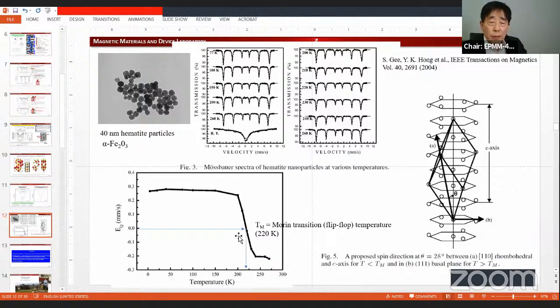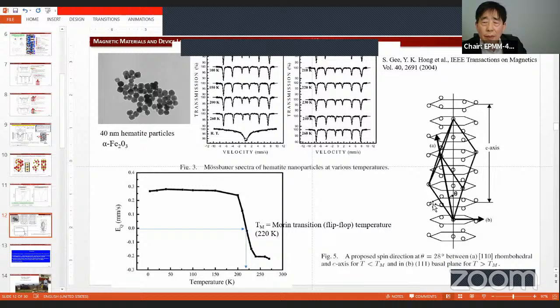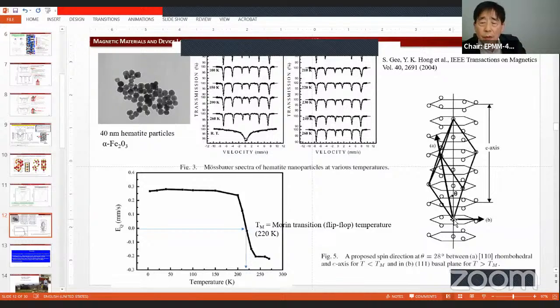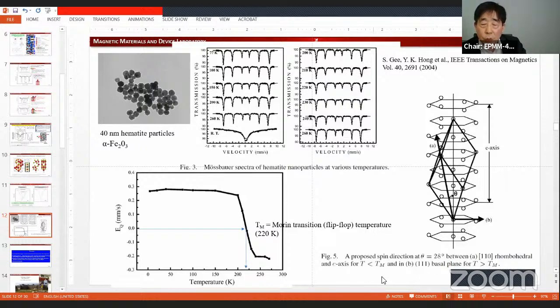Once we see the Morin temperature of 40 nanometer hematite nanoparticles, we identify the Morin temperature, originally the magnetic field right there, and the Morin transition temperature nearby. This is the magnetization going in that direction. And we identified that the angle between this z-axis and that shifted magnetization direction is 28 degrees. So Mössbauer spectrum can tell us the flip-flop angle as well.